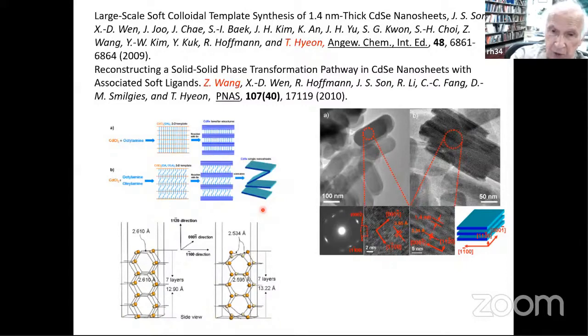These pictures, which are transmission electron microscopy pictures, do not show the ligands that, in fact, are responsible for the stability of these platelets and which are responsible for the kinetic barrier that this material has to going back to bulk cadmium selenide. So the moral of this is, do not show such pictures to innocent people like theoreticians without telling them that you're not seeing everything, that you're seeing just what my instrument sees.